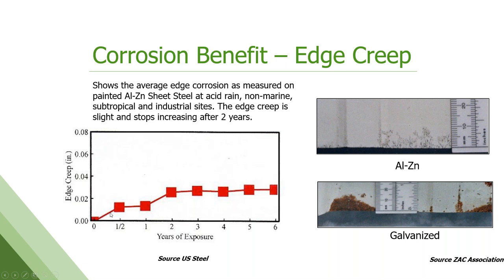That's what this graph shows here. It's progressing, but then it really levels out and plateaus after 2 to 3 years and slows down almost completely. One caveat here is that in those first couple years, galvanized does sometimes outperform the Galvalume product, but then there's an inversion of performance, and the galvanized will continue to corrode up this chart while the Galvalume goes flat. So we do see a reversal after the first couple years.